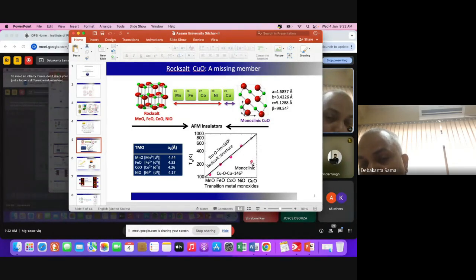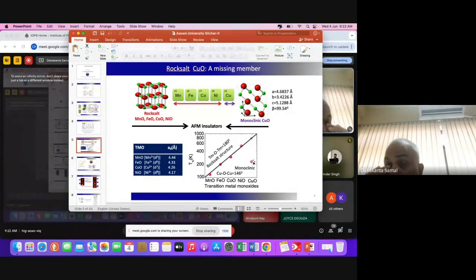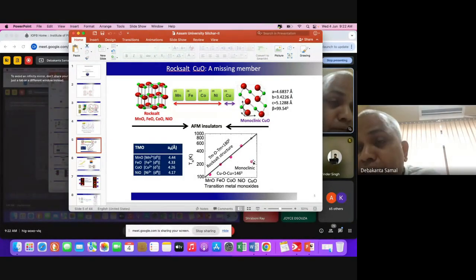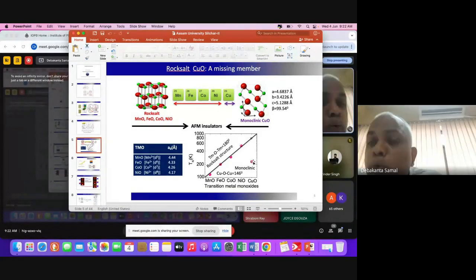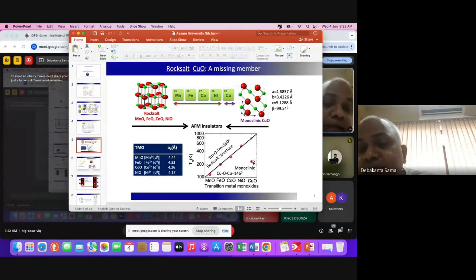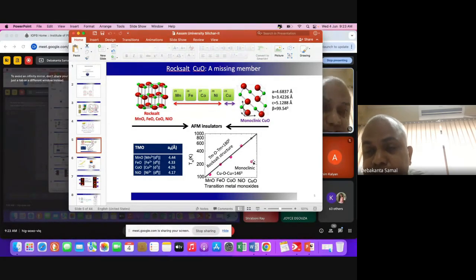But what we find in actual experiment is that copper oxide has a Néel temperature, a magnetic ordering temperature, much less compared to that linear trend. So why is that? It arises because the structure is different, because the magnetic exchange interactions are different. Now the question I am asking: nature does not give you copper oxide which is like rock salt, the left hand side. Nature gives you copper oxide which is very distorted. It is not a symmetric structure.